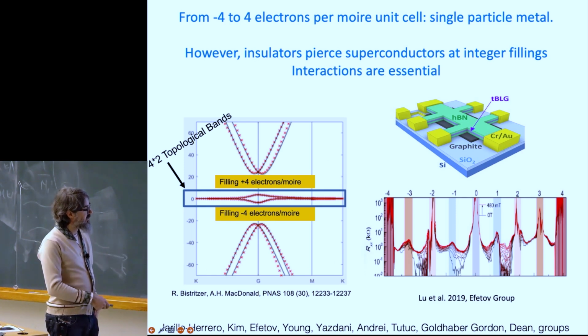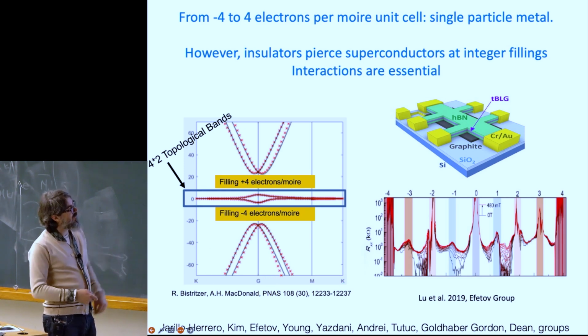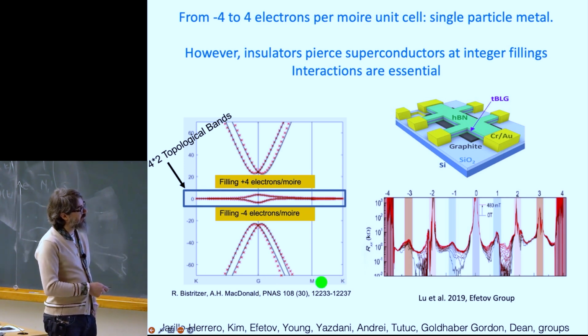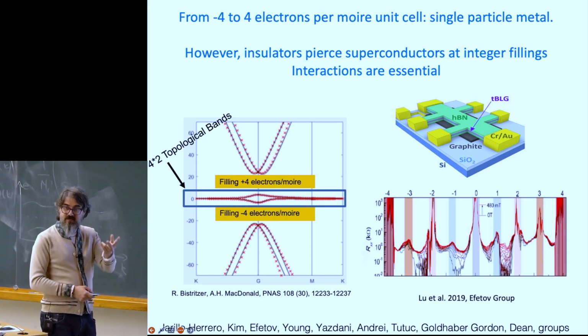So the unit cell is much larger, hence these momenta are much smaller than in graphene. But nonetheless, I can still plot the band structure here, for reasons that I can tell you. And you can see what happens here. You have two very flat bands at 1.5 degrees, two very flat bands. But in order to do the proper counting, we must remember that graphene has these two valleys, K and K prime, so we multiply it by another 2.